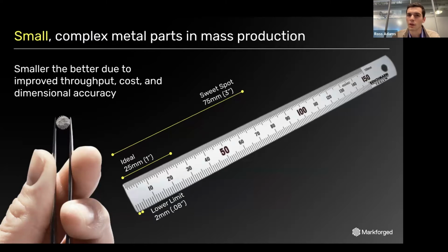Now, when we talk about the limits, the lower limit we'd like to say is greater than 2 millimeters. That's mostly a challenge of the depowdering process and being able to grab the parts and move them around to the next step of the process. We can go a little bit smaller, but 2 millimeters is a good governing factor. And then the absolute upper limit here, we say is about 150 millimeters. This is going to be a balance of high part cost and loose dimensional accuracy needing post-machining. In demanding applications, we've certainly done parts up to this extreme, but it requires a little bit more scrutiny when we think about the business case and if this process still makes sense at these types of part sizes. So, 1 inch or less, we've got something great. Less than 3 inches, we're on the right track. And these two extremes, we want to stay within. So small parts, the smaller the better.